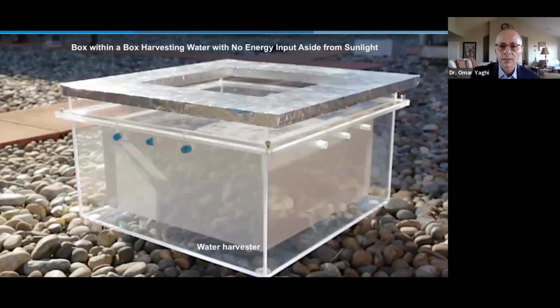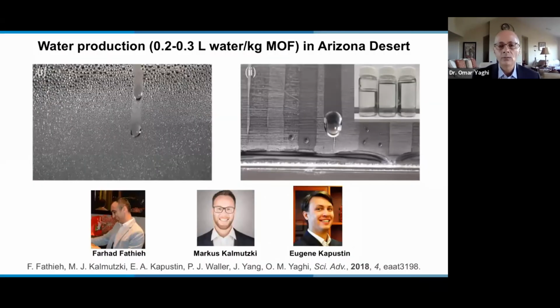This is what the box looks like. It's made entirely from simple materials like plexiglass, very inexpensive materials, and very cheap. And this is the result. The result is that in 1 kilogram of MOF, we can harvest around 200 or 300 milliliters of water, so a bottle of water for each cycle. The MOF can stay in the device for the lifetime of the device, for years.